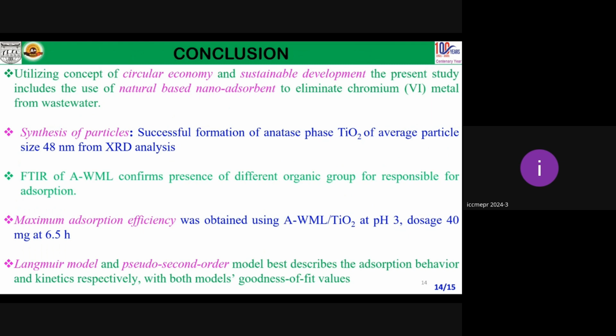So with this, I would like to conclude my work in a few points. Here is the concept of circular economy and sustainable development. This present study focuses on the usage of a natural-based nanoadsorbent to eliminate hexavalent chromium. XRD analysis confirms the TiO2 nanoparticle from the plant extract. From FTIR, different organic groups were observed for AWML, which are responsible for adsorption. Maximum adsorption efficiency was obtained for the nanoadsorbent. And the last one is that the Langmuir model and pseudo second order model best describe the adsorption behavior and kinetics, giving a good fit.